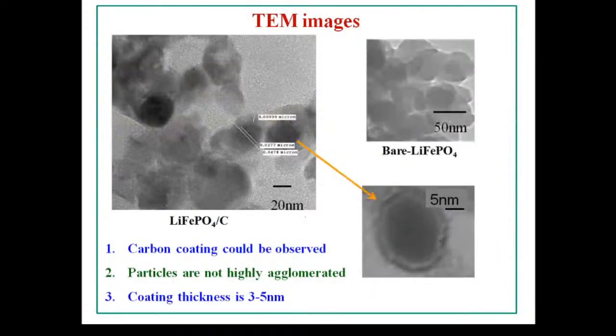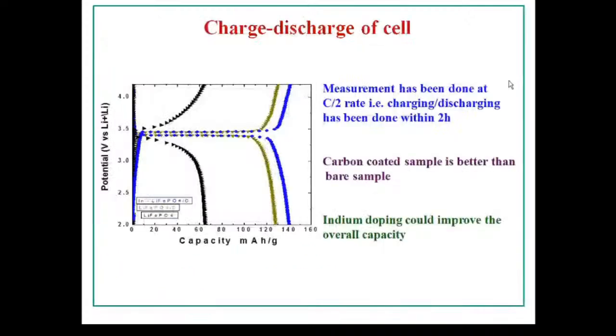You can see that we made these nanoparticles. They are coated with carbon, and you can see the carbon coating is also there. Whereas the bare LiFePO4 at the right side corner, you can see they are relatively big chunks, and I'll compare their performance to show how nanomaterial has given us the edge. Whenever I use the nanomaterial, the blue curve, the capacity is around 140 milliampere hour per gram. But the black one is around 65 or 70. That is the non-nanomaterial, the big particles. So making the material nano improves the performance. That's the point I would like to make.